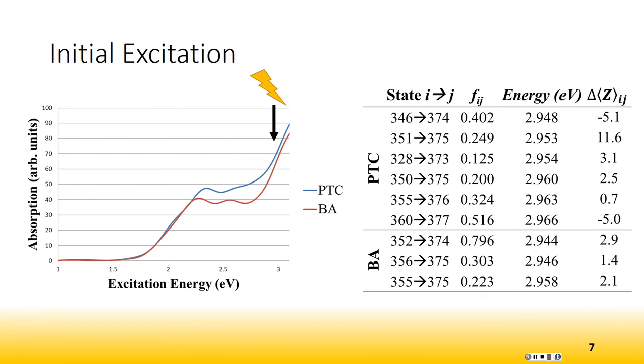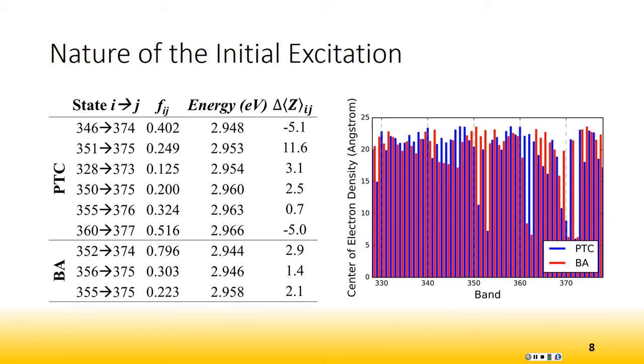And how we get this is if we look at the different states and then plot the center of mass. We can see here that it's localized on the ligand, and everywhere else on top is localized on the quantum dot. And we can see that a lot of the PTC are excited, the hole is in this region. So the BA has to relax down to almost a HOMO level to be able to get a charge transfer state.